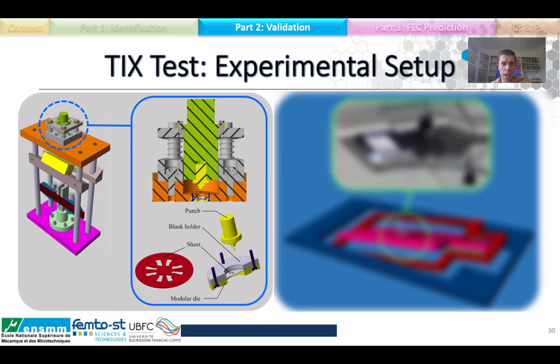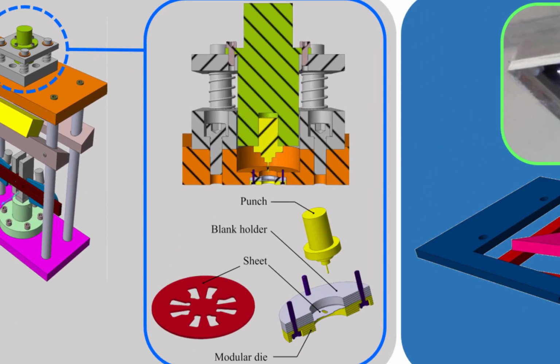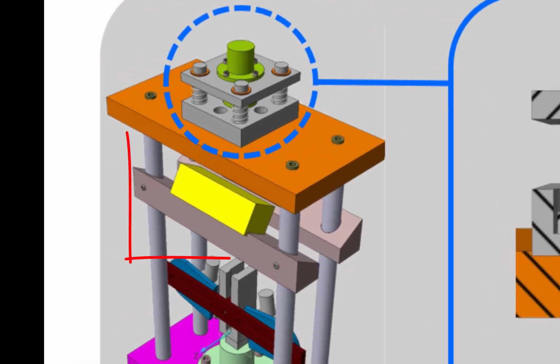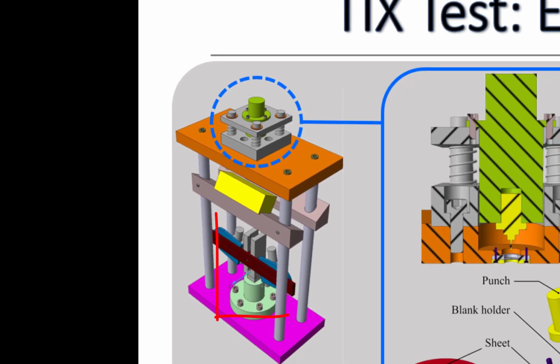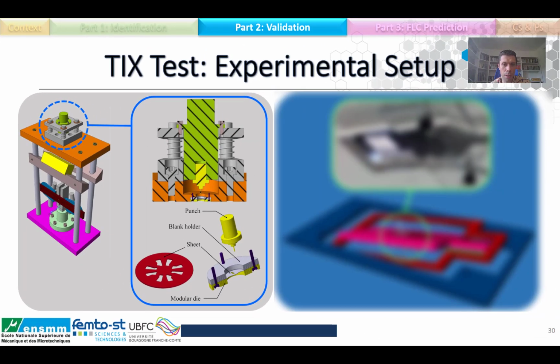For example, for the alignment between the punch here in yellow and the blank, the punch is no longer fixed to the tensile test crosshead, but to a column system with a counter spring. For lighting optimization, LED spotlights are adjustable independently of the camera. The cameras are fixed on the lower part of the setup here. And to resolve the last problem, which is the focus depth and blurry image, we use new lenses and we optimize the distance between the camera and the specimen.